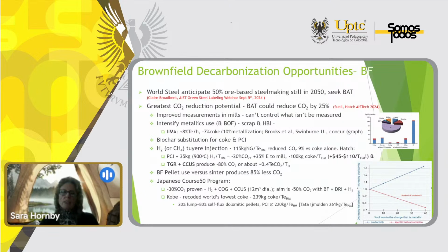And the International Iron Metallics Association has shown that an 8 tons an hour increase in productivity and a reduction of 7% coke can be gained for 10% metallization in the furnace. And Brooks et al. from Swinburne University in Australia have shown that to be also fairly accurately true by the graph at the right-hand bottom. Biochar can be used for substitution for some coke and also for the pulverized coal injection to the tuyeres. We can also put in hydrogen or natural gas as tuyere injection. And for 115 kilograms of natural gas per ton of hot metal, the CO2 can be reduced 9% versus coke operation alone.